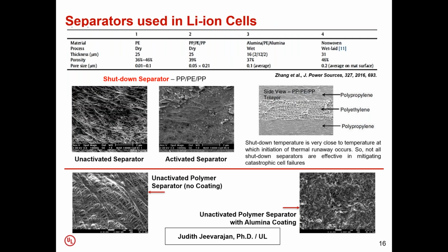One could use just a polyethylene separator, or the tri-layer separator, which was very common for many decades. And the tri-layer separator has polyethylene that is sandwiched between two layers of polypropylene. And with this particular design, as you can see from the picture below, it's called the shutdown separator, where on the left side you can see the pores in the unactivated separator. And this picture is a SEM picture, scanning electron microscopy picture, that shows the pores in the separator of a fresh separator.